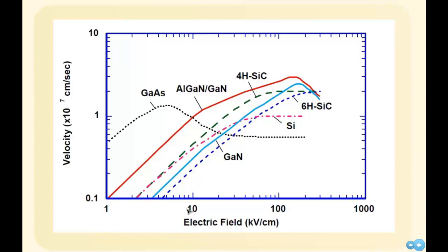So we're talking about less than 10 kilovolts per centimeter, maybe less than 5 kilovolts per centimeter, in fact. And we're looking at how well the electrons respond to fast-changing stimuli when their amplitude is relatively low, so a low electric field is applied. And we define a figure of merit, which is called the carrier mobility, and is defined as the slope of the curves that you're seeing on the screen, which represent the velocity versus the electric field, at low electric field